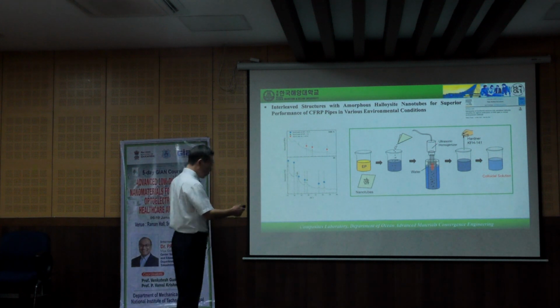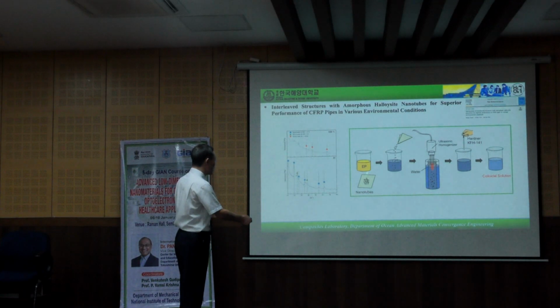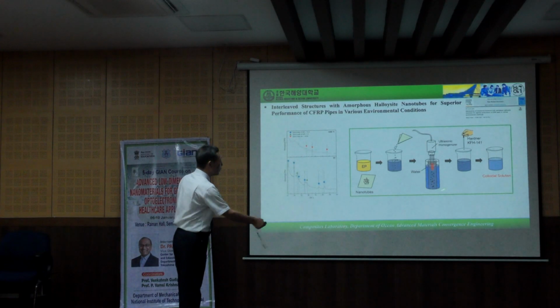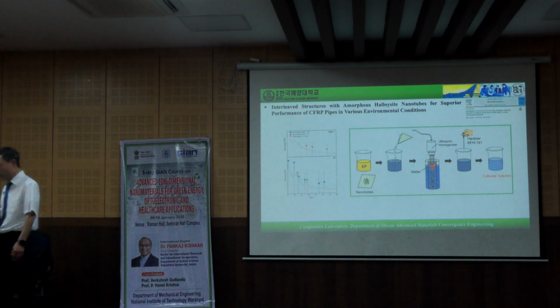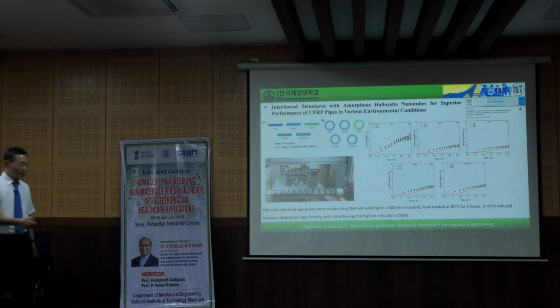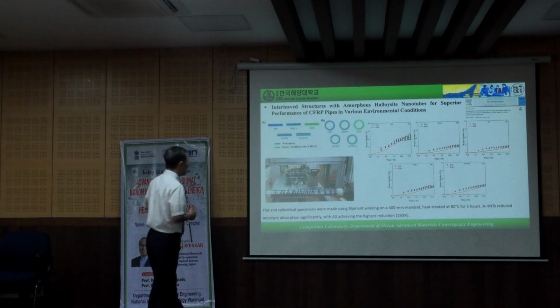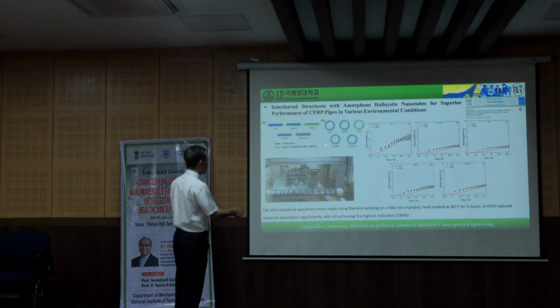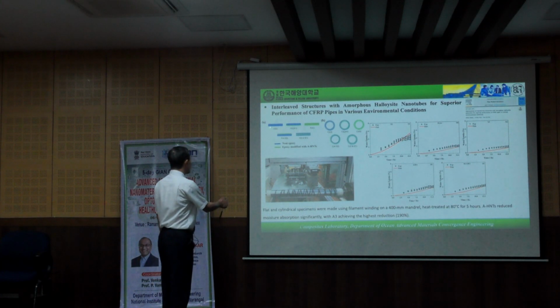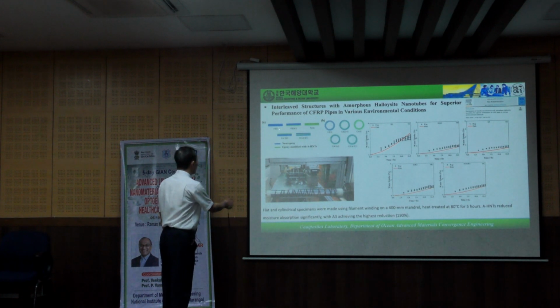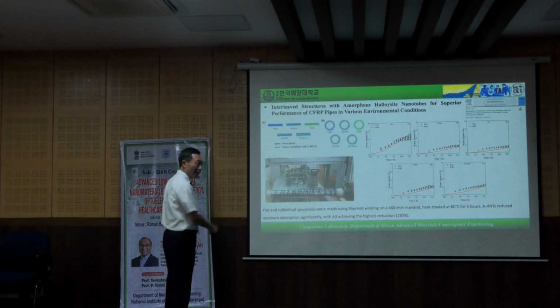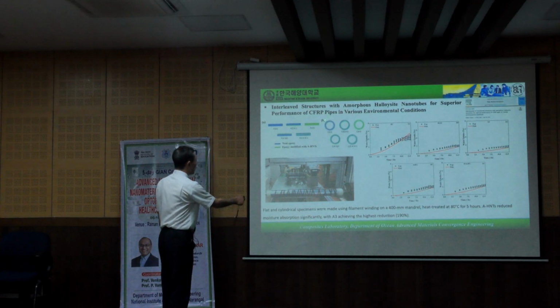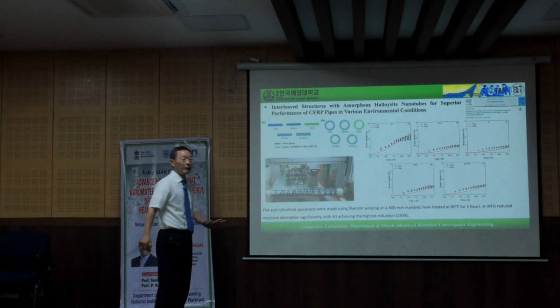So we prepare the specimen, epoxy, nanotube. In case of a pipe composite, we prepare the 5 kinds of specimen. E3 means three layers of neat epoxy, and E2A1 means 2 layers of neat epoxy and amorphous 1 layer. So we designed like this, 5 kinds of specimen.